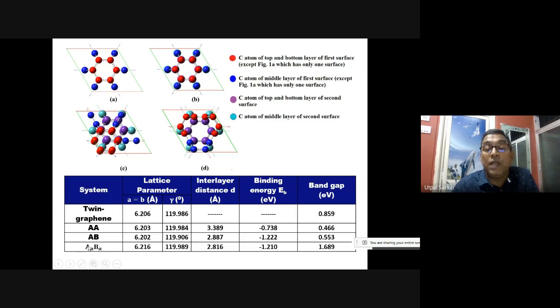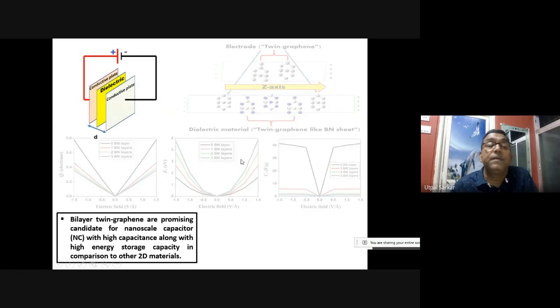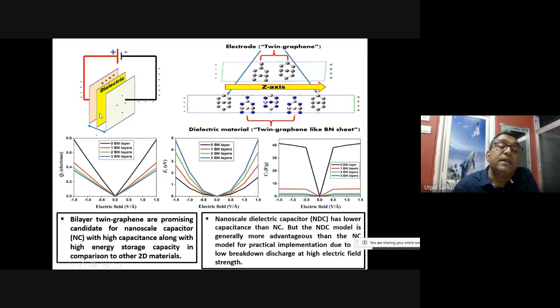So we have considered different stacking modes, and we have calculated the lattice parameter, interlayer distance, binding energy, and band gap for these structures. We inserted this dielectric material here, applied the electric field along these directions, and measured the capacitance. So these are the charges. This is 1 dielectric medium, 2 dielectric media, 3 dielectric media, and so on. Here we have not put any dielectric medium, that is only a nanoscale capacitor, separated by 2 electrodes.